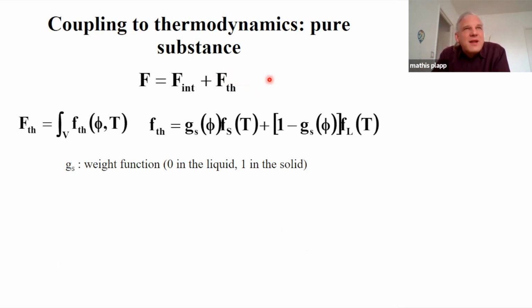Assume that it is the same, and then the only variable that is relevant for a pure substance is the temperature. And so the thermodynamic part of the free energy, I can write this as the volume integral of a free energy density. And well, I know that I have two phases, solid and liquid. So my thermodynamic part, a free energy density, is the free energy density of the solid if I'm in the solid, and the free energy density of the liquid if I'm in the liquid. And so my function G of the phase field, this is just a weight function that is 0 in the liquid and 1 in the solid. Okay, and since the order parameter varies smoothly, this weight function also varies smoothly through the interface.